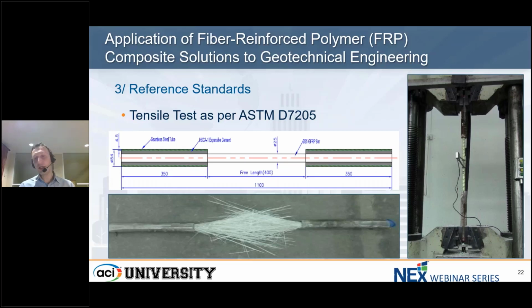Obviously, as we can see here on the sample after failure at the bottom of the screen, this material is brittle. That's again well known to people who design with ACI 440.11, but you have to imagine when we are moving into the geotechnical world, very often designers are not familiar with that. The exposure to composite material in those ground engineering applications is much less than what we could see with RC structures. And so a lot of the education work that has been done by the ACI 440 committee has to be addressed and transferred to geotechnical work.